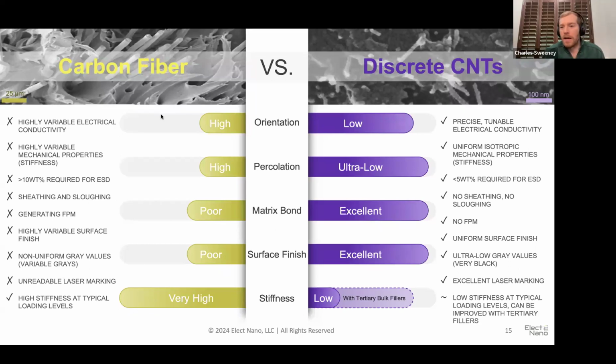And that's a problem because as chips are put in and out of these things, and as the trays move around or rub against each other, tribo charging and electrostatic charges can build up in these components. And the interesting thing about computer chips is that generally as time goes on, they become more susceptible to ESD damage, not less, because the transistors are continuing to shrink in size. And that means that the amount of voltage that they can withstand before they have a breakdown event actually goes down.